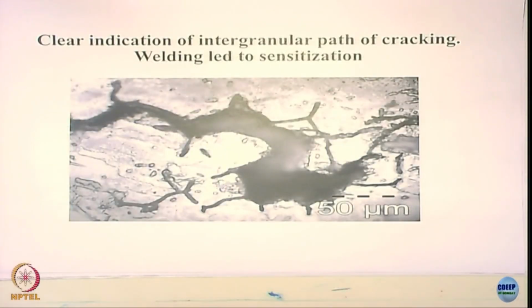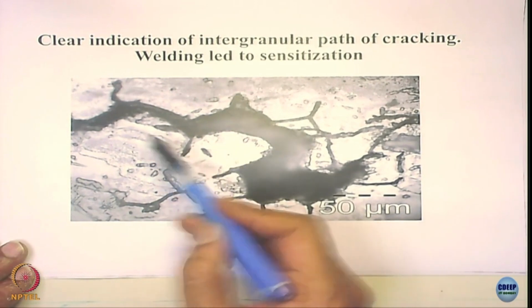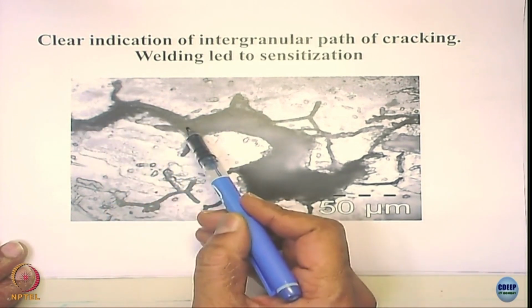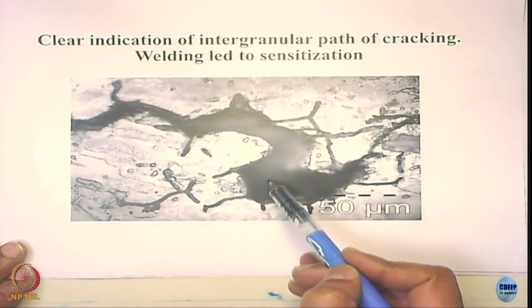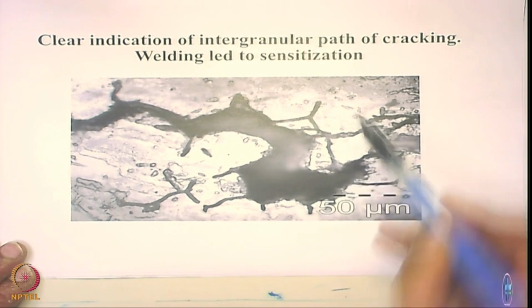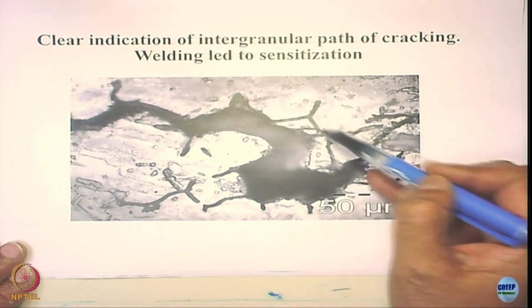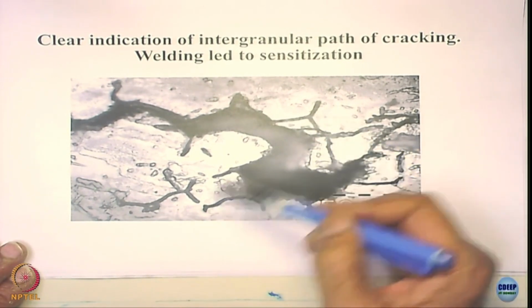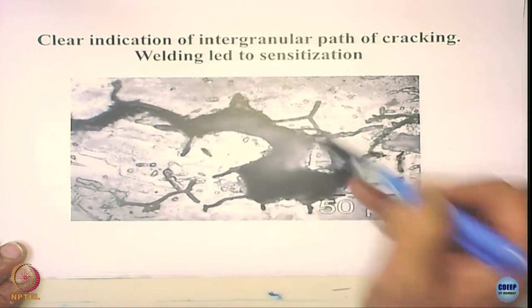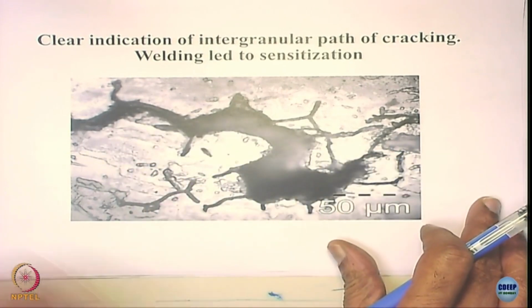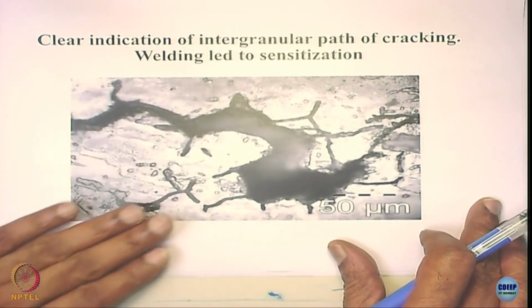Look at this, it's a clear intergranular crack. Look at the grain here, the crack grows along the grain boundary. Why? The grains have got sensitized. You can see this here. The grains got sensitized, and the crack grows along this. So it's the surface of the specimen, see that.